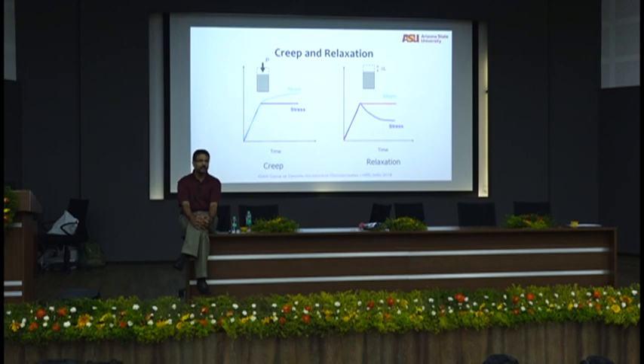What is the only thing that can save you from this higher stress? Relaxation, right? What do you want for relaxation? A lower elastic modulus, right? Very stiff materials don't relax. You want a lower elastic modulus for relaxed stresses. Now look at the paradox. Immediate gain, reducing cross-sectional area, giving more plinth area to the builder and developer so that he can sell more square feet of space. High strength is a very fancy term that everybody loves.